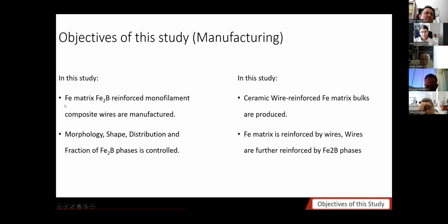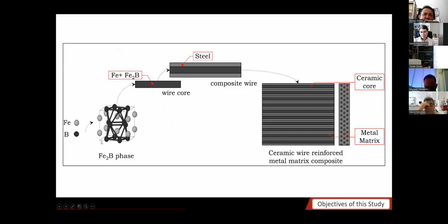So the objectives of this study are Fe matrix, Fe2B phase reinforced monofilament wires manufacturing, in which the morphology, shape, and distribution of the fraction of the iron boride phases are controlled. And then ceramic wire reinforced bulks are produced in which the Fe matrix is reinforced by the wires at a macroscopic level, and the wires are further reinforced by the iron boride phases. This is the type of material which we are anticipating. Atomic level, iron boride phases inside the core of a wire. The core is going into the steel, and a composite wire is produced.